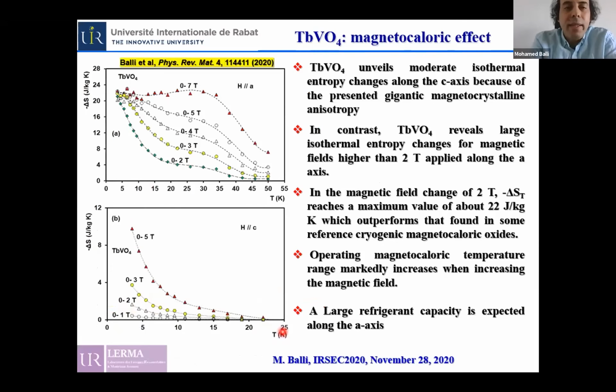Here is given the entropy change as a function of temperature in the terbium compound along both the A-axis and the C-axis. A giant magnetocaloric effect is observed in these materials at very low temperatures, particularly around 5 Kelvin. For example, for a magnetic field change from 0 to 2 Tesla, the entropy change reaches a value of 20 joules per kilogram Kelvin.